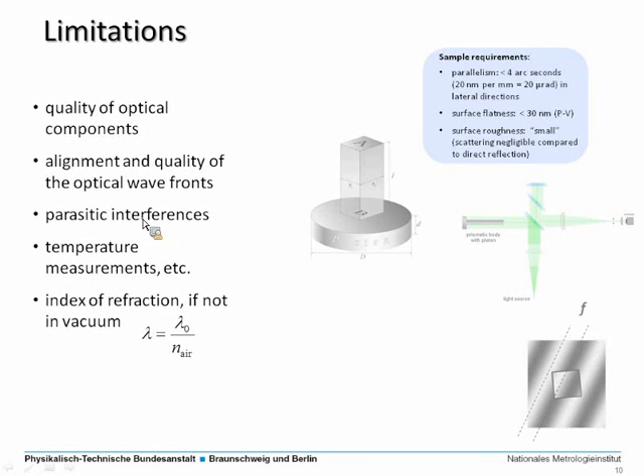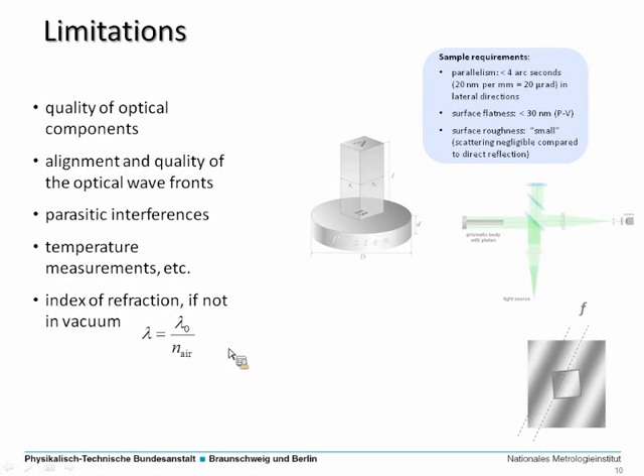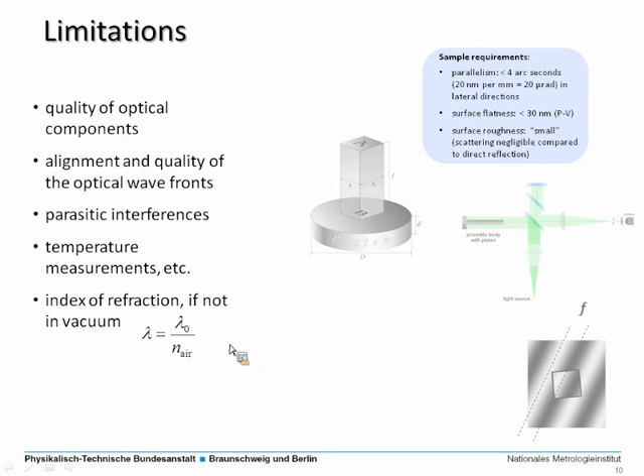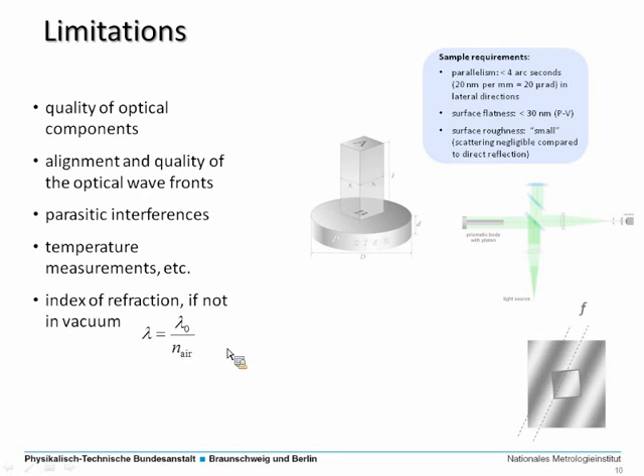Together with the alignment, you can get parasitic interferences, and of course also temperature measurement is important for length measurement, especially for materials which have a high coefficient of thermal expansion, because then the influence is larger. And if you are not working in vacuum, also the index of refraction of the surrounding air is needed in order to take this into account.